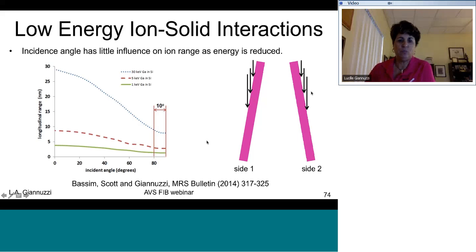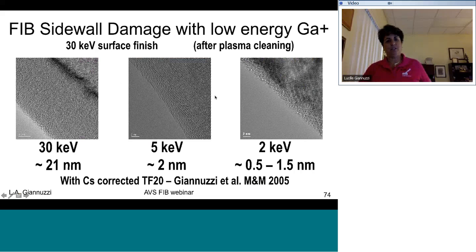So this means that we can work with 10 degrees or so if we need to. If we need to just see where that sample is, we can go to greater angles relative to the sample surface, and tilt and be able to see where we can put our ions. So this is just the experimental work that we did years ago that shows that you can decrease the sidewall damage by going to low energy. This is no surprise these days.